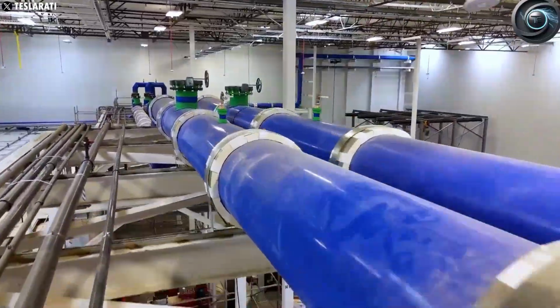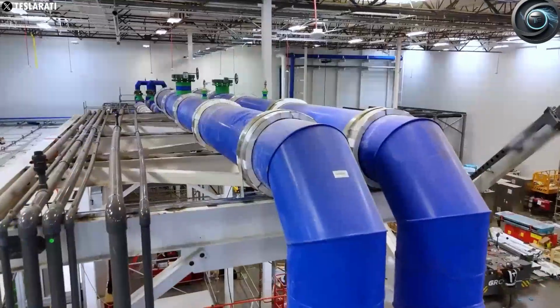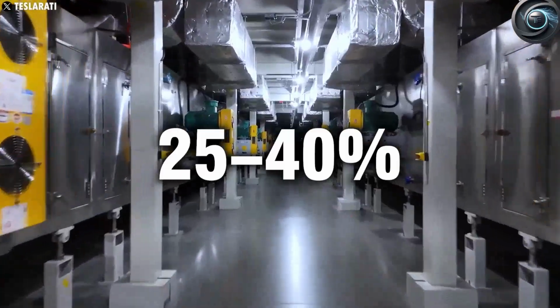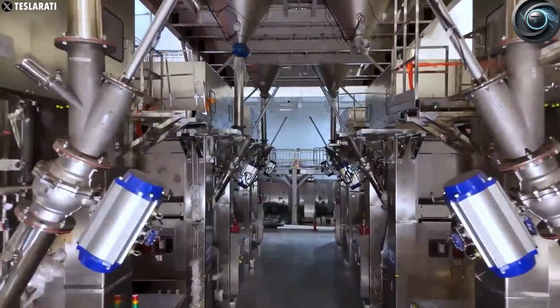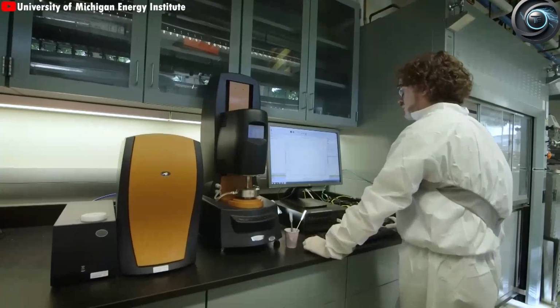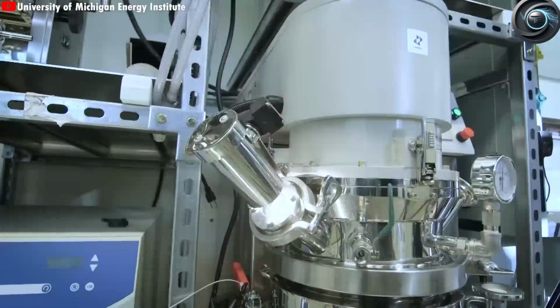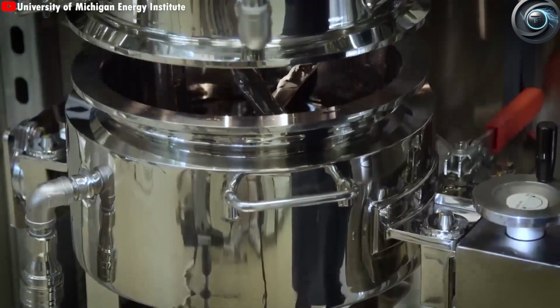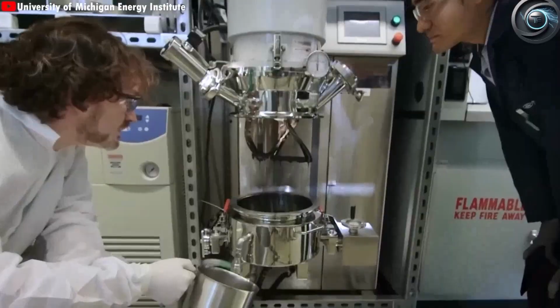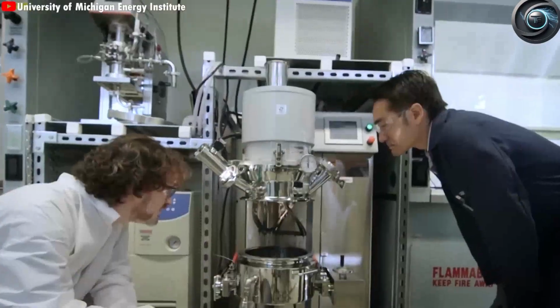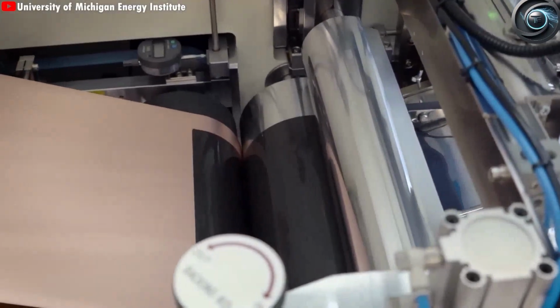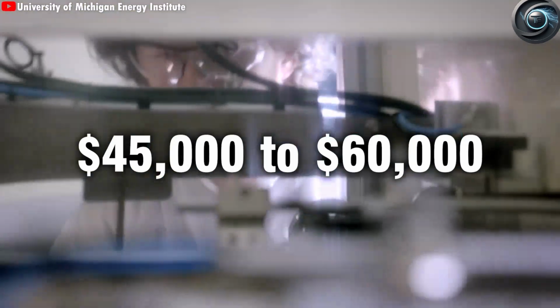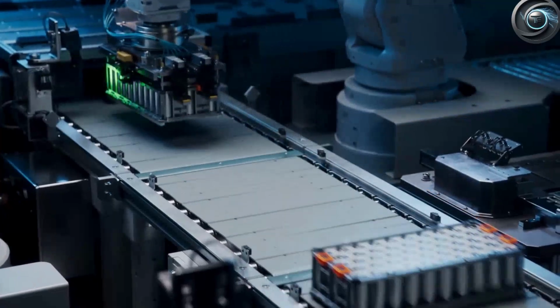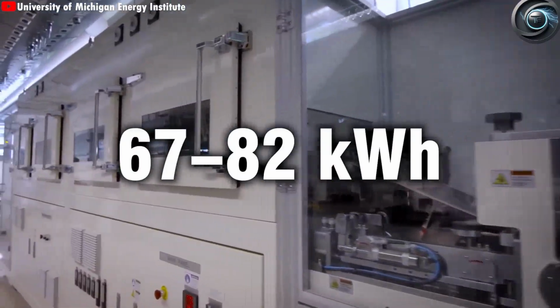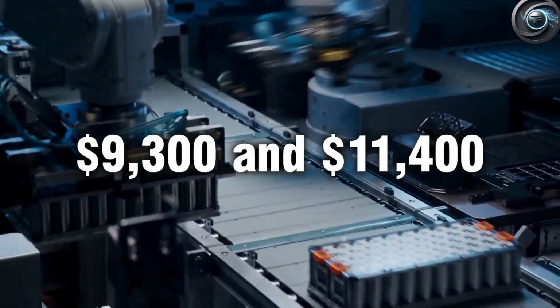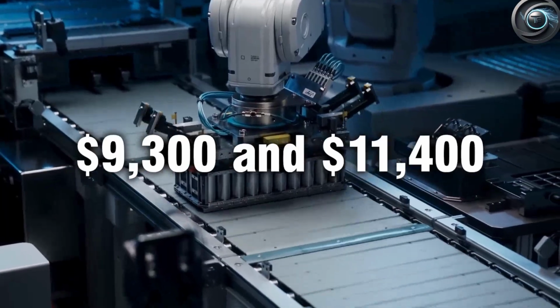Take the Model Y, which uses between 67 and 82 kilowatt hours of battery depending on variant. If we assume a lithium pack cost of around $139 per kilowatt hour, that places the battery cost somewhere between $9,300 and $11,400. Now imagine replacing that with an aluminum ion pack at $55 per kilowatt hour. Suddenly, the battery cost drops to around $4,300. That's a savings of $5,000 to $7,000 per vehicle. That cost reduction alone could be the key to unlocking a sub-$25,000 Tesla.